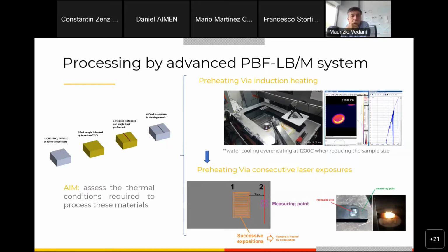So to do this, we first designed and integrated a heating device, an induction heating device that you can see on the top right side of the screen. It was designed and integrated in the powder bed fusion system. However, with this system, we were only able to reach preheating temperatures up to 1100 to 1200 degrees C. So for this reason, and as we still observed cracks in those samples, we proposed a novel approach, which is the one on the bottom part, on the right, which is heating the sample with consecutive laser scan tracks nearby the area of interest.